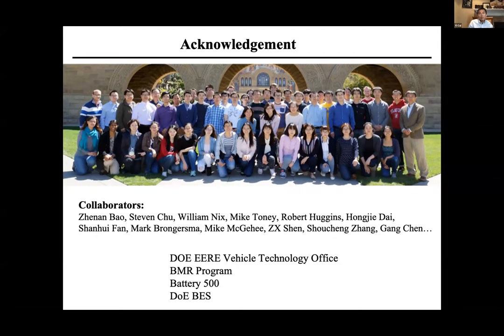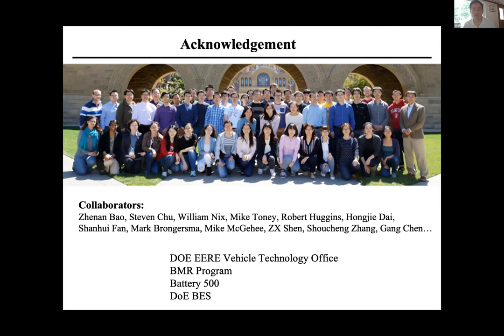Fluorine chemistry is already used in current lithium-ion batteries — LiPF6 salt and fluoroethylene carbonate additives are common. The FDMB molecules are actually very simple to synthesize in large quantities — it is a one-step synthesis, so scaling and cost should not be an issue. That said, we need to be careful about fluorinated carbon's environmental impact. I think battery recycling and reuse recycling is critical — we are still far from having economical methods. DOE has started a recycling center at Argonne National Lab, mostly for valuable cobalt, nickel, and lithium. With fluorine, we need ways to recover it and not release fluorinated compounds to the environment.